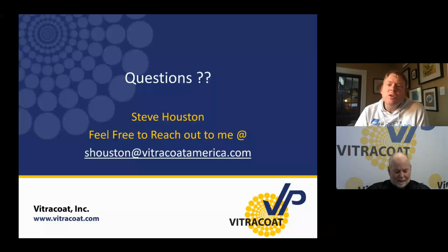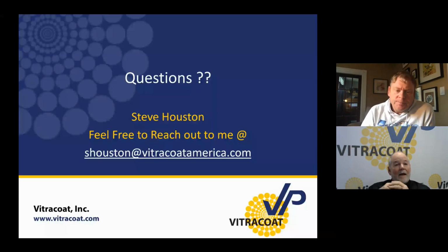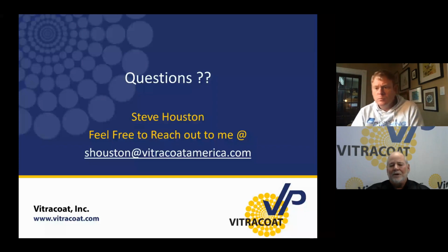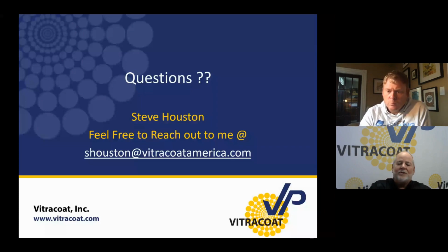What is a minimum cure time in most applications? Well, there's not one. I can say typical is 10 minutes at 400 degrees. And when they say 10 minutes at 400 degrees, it's not like baking cookies, like throwing them in the oven for 10 minutes at 400. The part needs to come to temperature, 400, and be held there for 10 minutes. So if my part mass is significant, it'll take time in the oven to get up to that temperature. And I think that might be some of the reasons why cure is pretty prevalently a problem in powder coating.